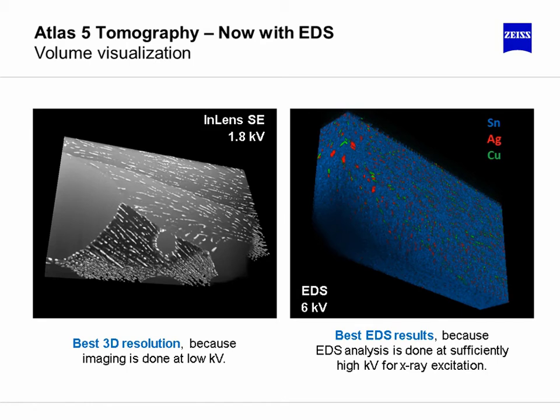On the left side, you see the reconstruction for the in-lens SE data acquired at 1.8 kilovolts, featuring the best possible 3D resolution because the imaging was done at a low kilovoltage. And on the right, you see the EDS results. The EDS maps were acquired at 6 kilovolts. This means the landing energy was sufficient to generate the needed X-rays.